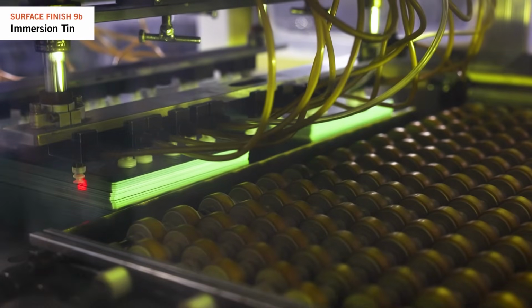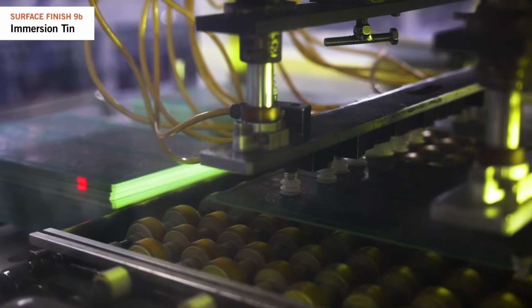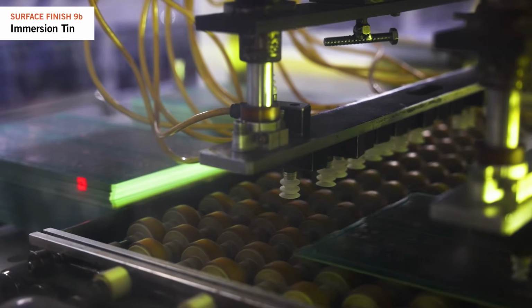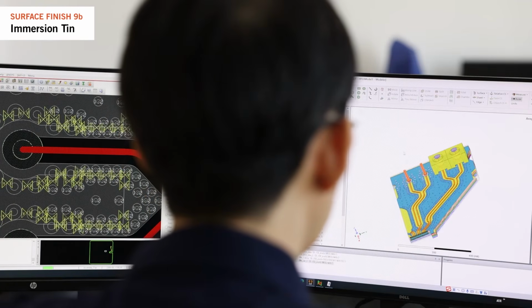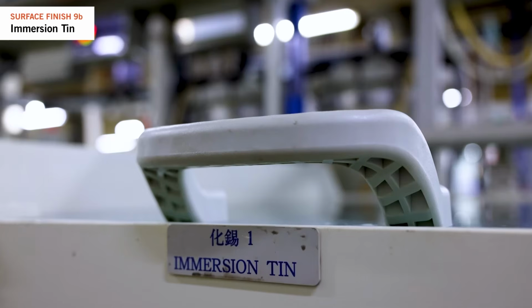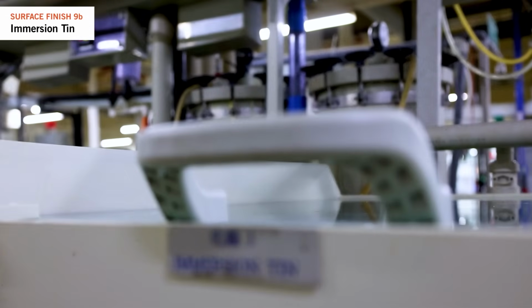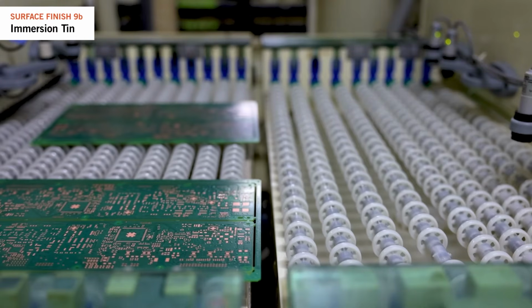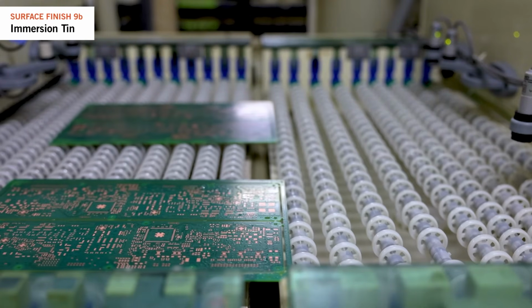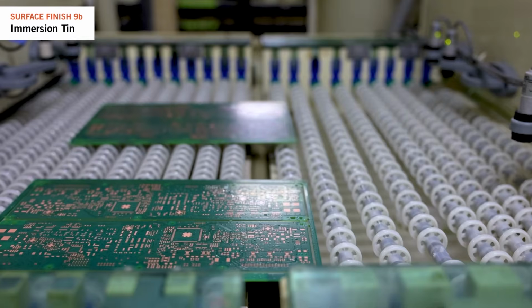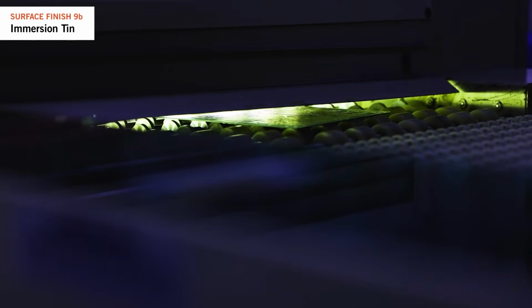Immersion tin is a more affordable surface finish compared to ENIG and is often chosen for applications involving press-fit pins. It is better for the environment, but some chemicals used in the process require strict control to prevent contact with humans. Contrary to the ENIG process, this is a horizontal process. First, panels undergo a UV bump to fully cure the solder mask, as uncured ink may react with the tin chemistry and lead to soldering problems.